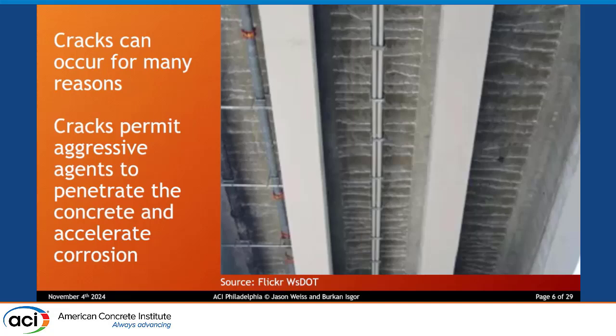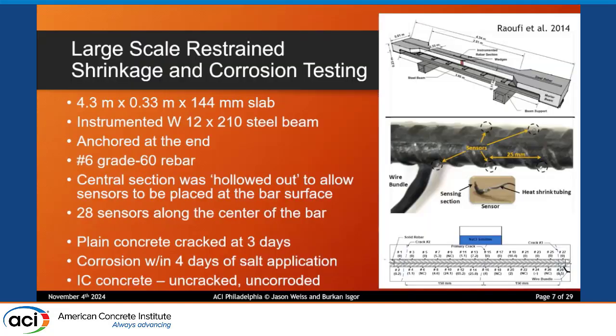And you may say, well, why would we want to reduce cracking? Is cracking really a problem? This is the underside of a bridge deck, right? And some of you may say, that's very attractive. Somebody got up there and they painted those white lines every 2.5 feet. No, that's calcite that's coming through cracks in those bridge decks, all right? And why is cracking such a big issue? Well, it's a big issue because it allows aggressive agents to get in, mostly chloride ions, mostly other things like that. So when we start to look at this, we don't want to lose sight of the important aspect of internal curing, which is reducing cracking.